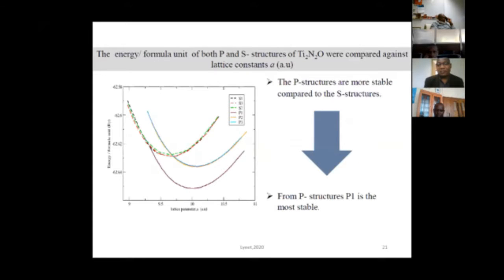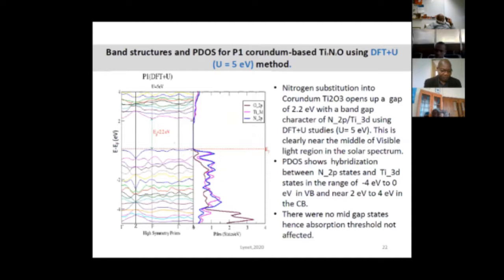So now we have the S and the P samples, and we want to check and see which ones are more stable. So we check the energy per formula unit and the lattice parameters and got that the most stable ones were the P structures. And remember that in the P structures, P1 was the most stable. So we decided to study the band structure of P1, which is the most stable sample.